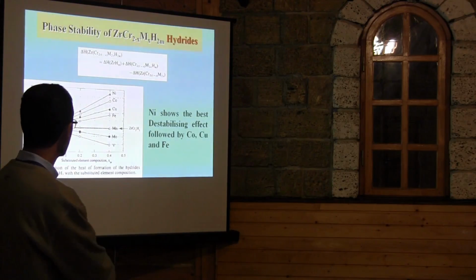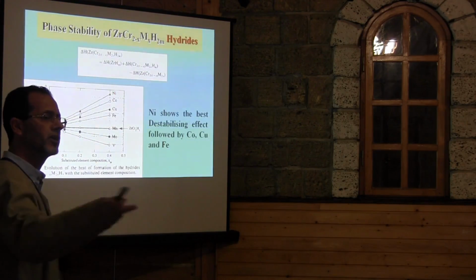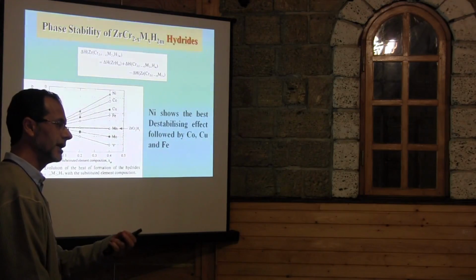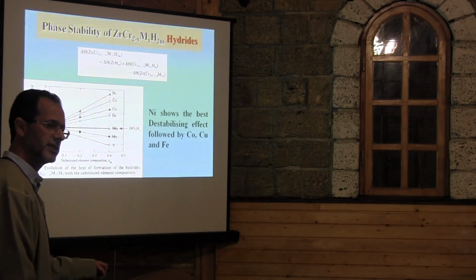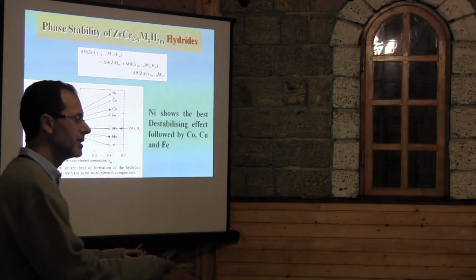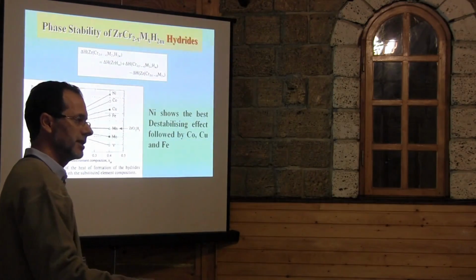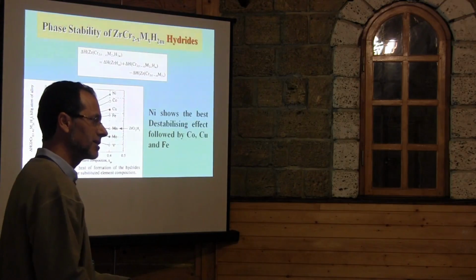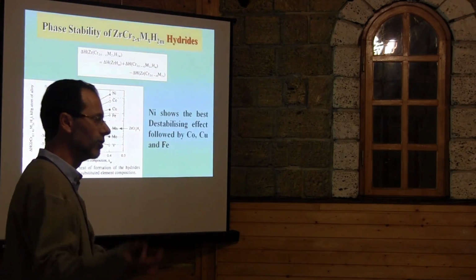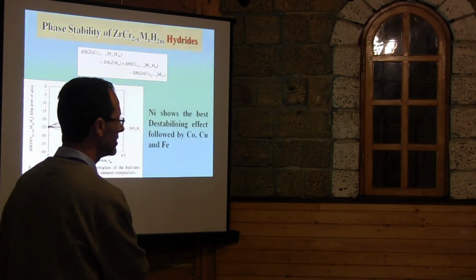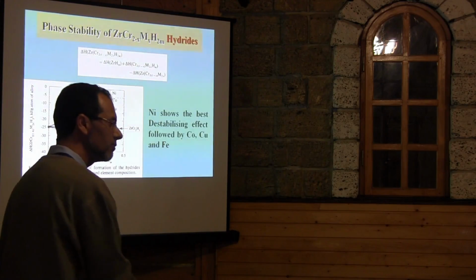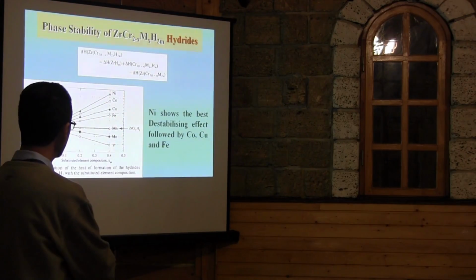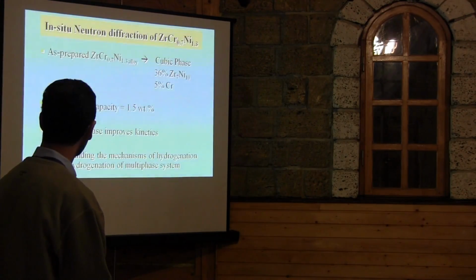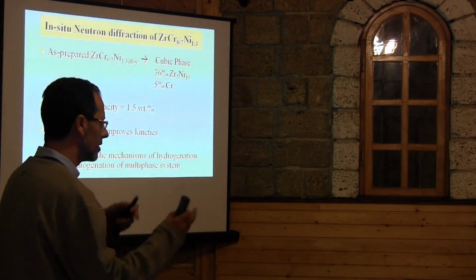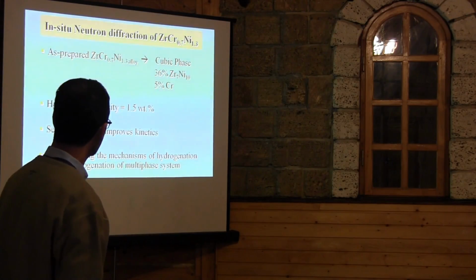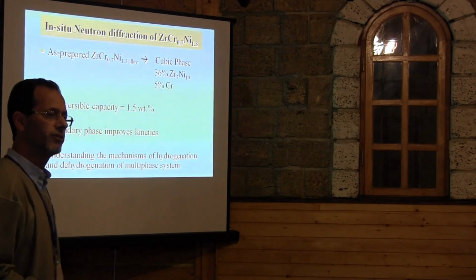I don't want to imagine how many elements I have and how many compositions I need to prepare. So I use some kind of modeling, like DFT, density functional theory, or this simple method. Before I ask to prepare many samples, which is time consuming and expensive, I can make a prediction of where to go. So now I don't need to go in this direction, I prefer to do it with nickel. And that's why I chose nickel in my center, because I did this investigation before. So now I choose this composition among the others, because I did a lot of work. We found that this composition is very suitable for